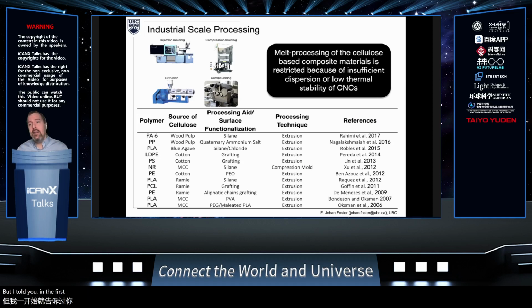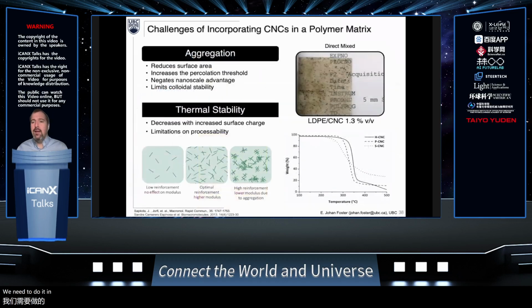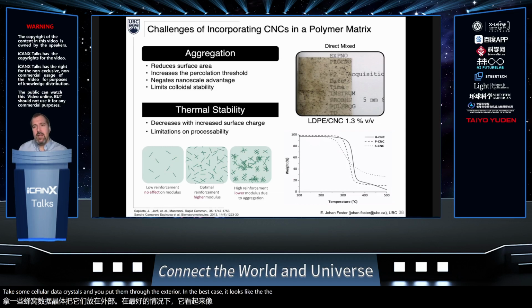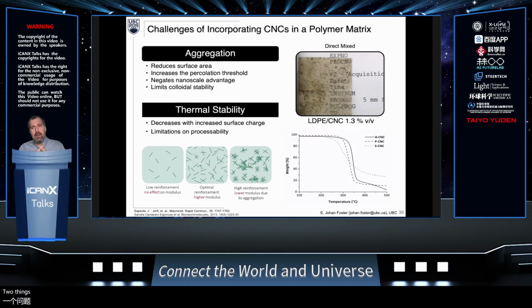But I told you in the first half of this talk that all of that great reinforcement we get is because of those interactions. How do we get our cellulose nanocrystals or our fibers into a polymer without disrupting that? Well, we need to do it in kind of interesting ways, because bad things happen. So in the case of our LDPE, if you take our low density polyethylene and you take some cellulose nanocrystals and you put them through the extruder, in the best case, it looks like the image in the top right. In the worst case, the whole thing turns black and it's a big mess. But in the best case, you can see sort of that degraded cellulose within that polymer matrix. The cellulose is aggregating, it's burning. This is problematic. So, two things: sticking together, so the aggregation, and the thermal stability of our cellulose becomes problematic.